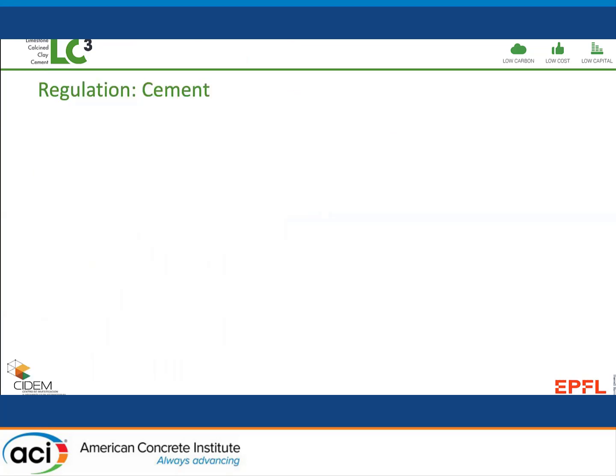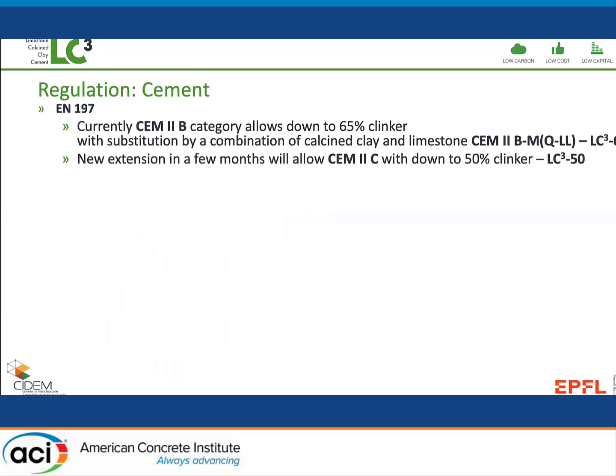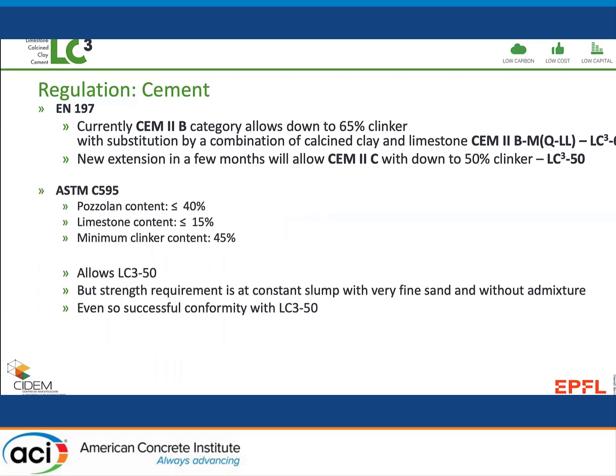So regulations in Europe, we've seen this change in the standard this year, which allows now to go down to a clinker content of 50%. In North America, and much of Latin America, we do have already ASTM 595, which would allow LC3 50. But this is really not being used. Really, people are using additions at the concrete level, which would favor LC3.